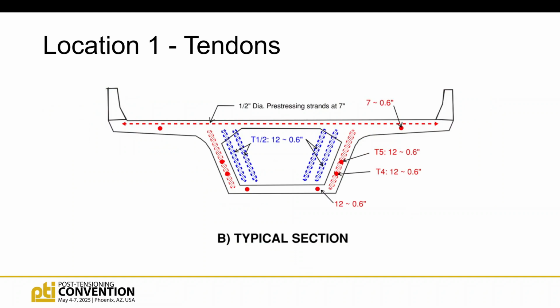Cross-section of the bridge looks like this. You have the half-inch diameter pre-stressed strands at 7 inches across the top. I show the blue externals. Actually, they were 12-strand tendons, my apologies. And the internal tendons in the webs. And those are the ones we lost.